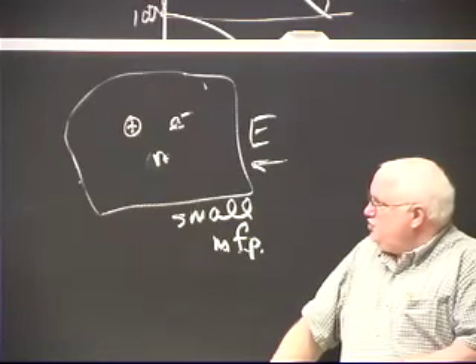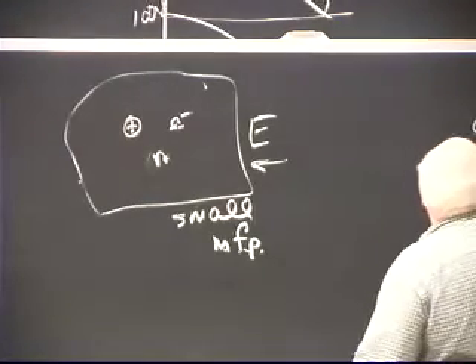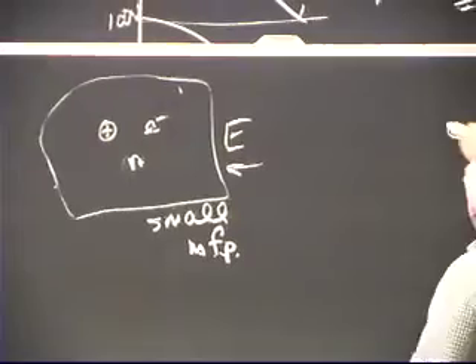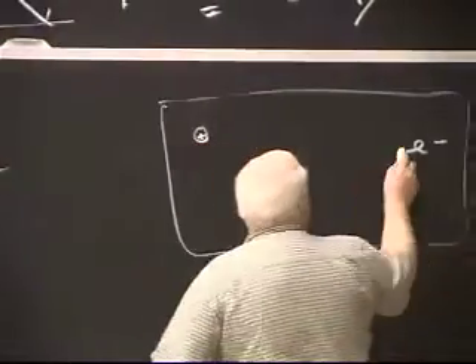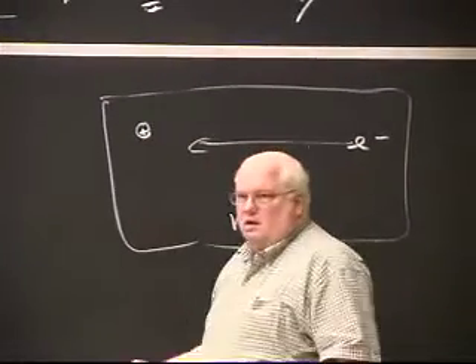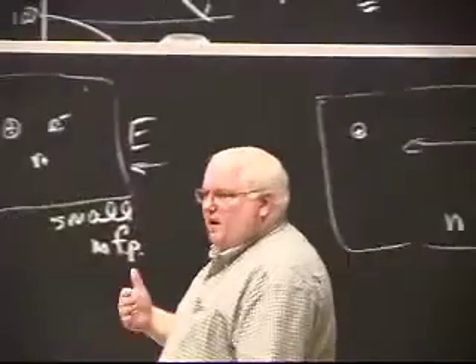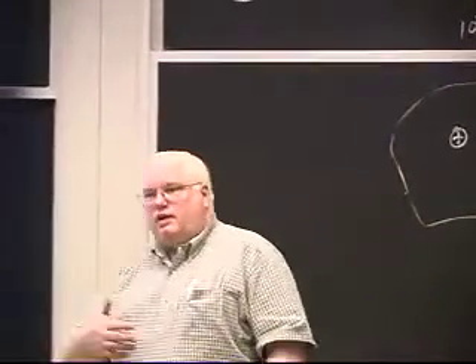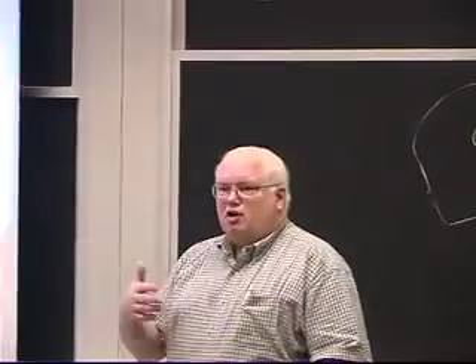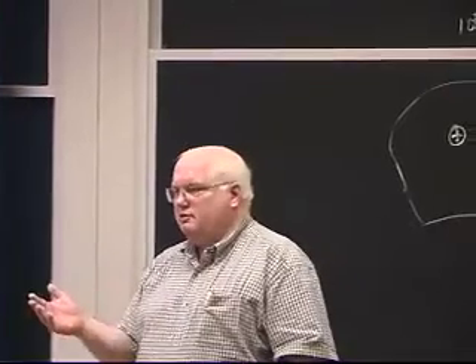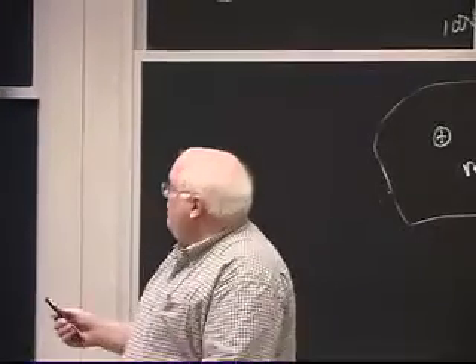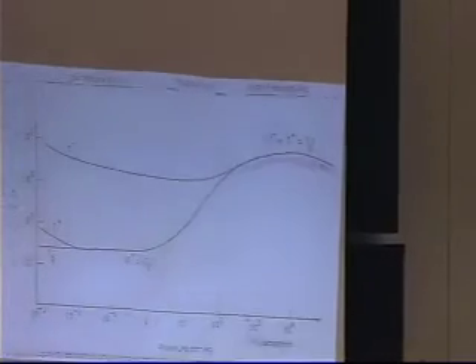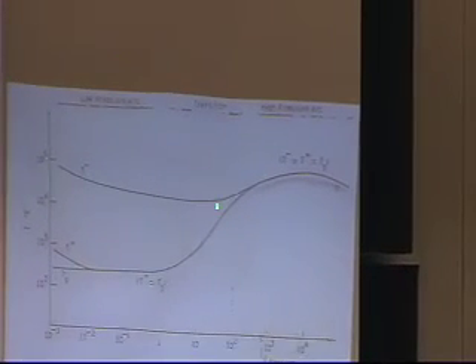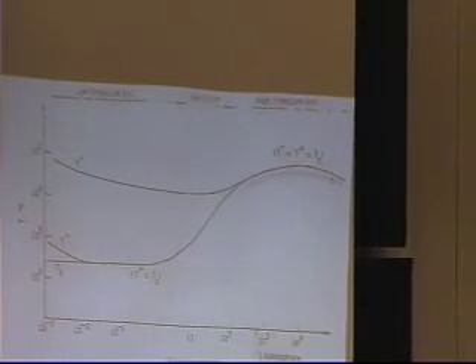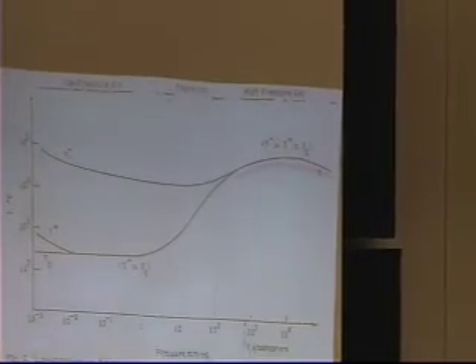As you get to lower pressures, now you get to the point where these things are so far apart in this chamber, that an electron can go zipping along, getting very high velocities, very high effective temperatures, whereas these other guys that are running around like molasses don't pick up, well, the neutrals don't pick up any energy from the field. The ions pick up some, but not as much. And so it turns out you start to get, as you get to lower and lower pressures and larger mean free paths, you get to the point where the electrons end up with much higher temperatures than the ions. And that's a fluorescent light.